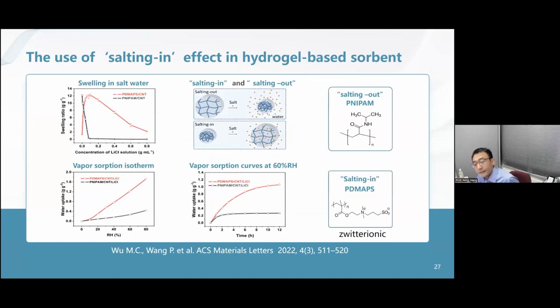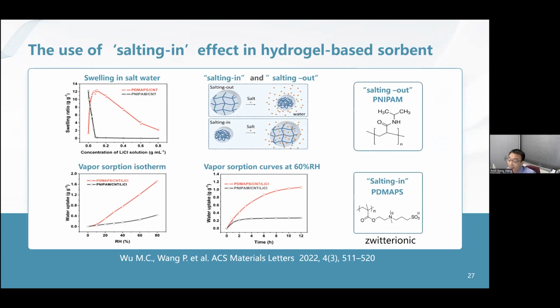And last year, we realized that this well-known salting-in effect, if properly utilized in hydrogel-based sorbent, can enhance atmospheric water harvesting efficiency and can help us produce more fresh water from dry air. In our case, we design polymers with both positive and negative charges within the same backbone of the polymer. In that case, we call the polymer a zwitterionic polymer. So we reported this work last year.